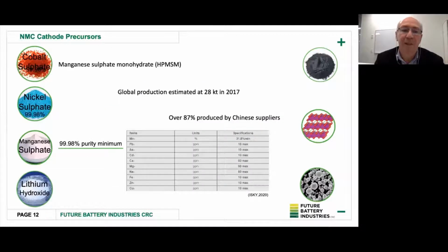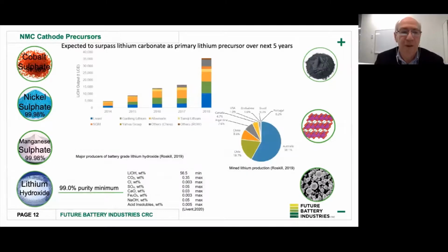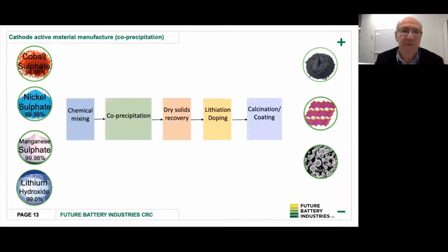Manganese is not produced in Australia in great amounts, and over 87% is produced by Chinese suppliers. Again, its purity needs to be 99.98%. If we look at the amount of lithium hydroxide being produced, Australia is the leader in this area. And it looks as though this material will be particularly lithium hydroxide rather than lithium carbonate, which will be required for batteries.